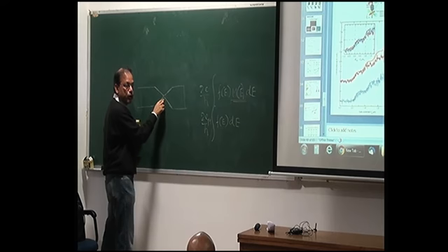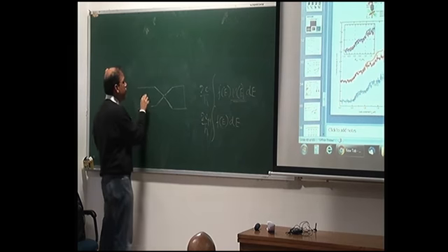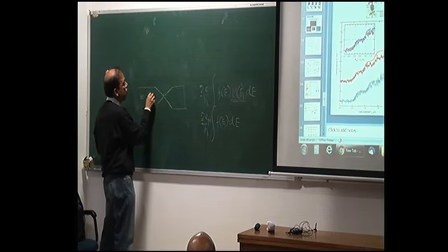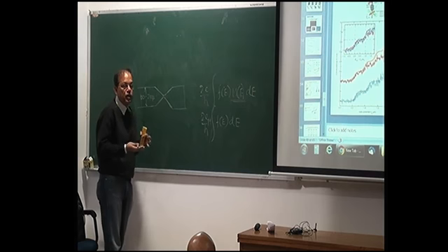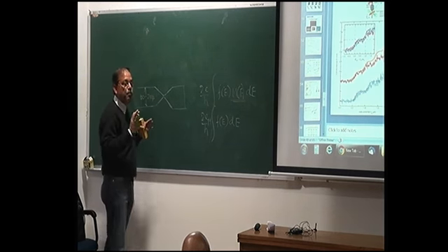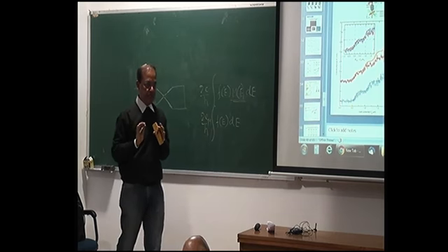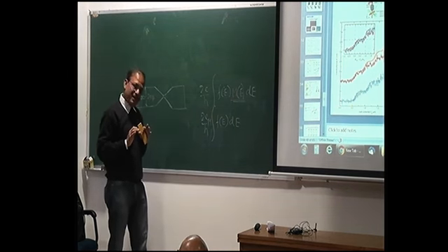If you use photolithography, then make it 1 micron. You can make it 2 micron also. And this 100 to 200 micron. And this length depends on how many devices you want to put on a single chip. But make sure this is not more than 2 micron. Even if it's 1 micron, you can get a gap of less than 5 nanometer.